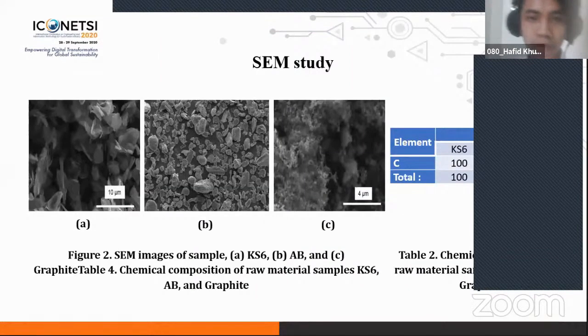Next, this is the SEM study from this picture. The KS6 raw material has a flake shape, similar to cornflakes, which are very uniform, ranging from 1 to 3 micrometers. The raw material AB has a spherical agglomerate shape ranging in the nanometer range, or we commonly call them nanoparticles. Graphite raw material has a slightly rock shape or roughness and is a primary grain with size in the range of 10 to 50 micrometers. The chemical composition of all the raw materials consists of 100% carbon as shown in Table 2.